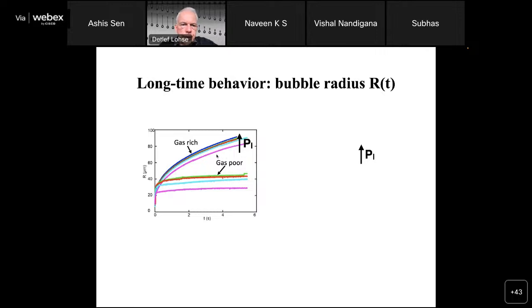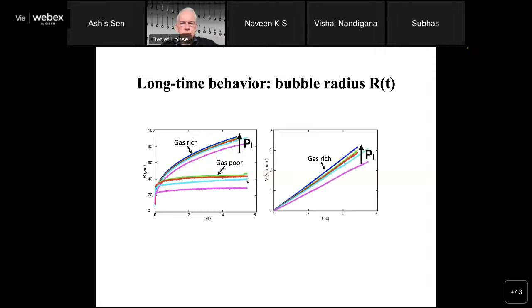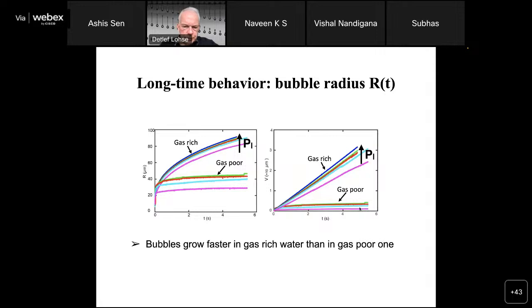Here we now compare the radius as a function of time for gas rich and for gas poor. For gas rich, it simply grows and grows. For gas poor, it comes to some saturation. For the gas rich case, the growth is simply linear in time. This is perhaps what you would expect. And for gas poor, the growth stops. It plays really a major role.